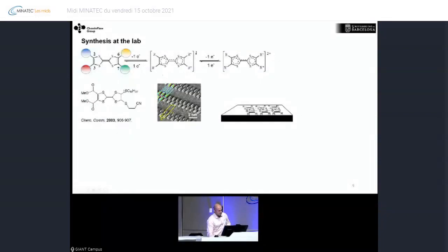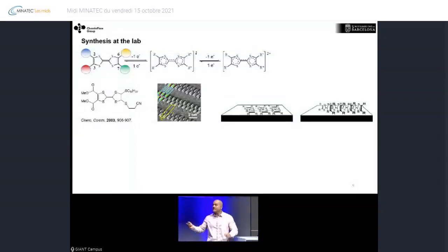As you can see here, with a very long alkyl chain, this is the STM image. What you see here brighter is the part of the molecule with the higher electronic density. So what you see here is that the molecule is lying flat on the surface. And this is not what we want. What we want is to have this type of organization here, where the molecules will lie perpendicular to the surface, where we will have this pi-pi stacking. So how to do that?